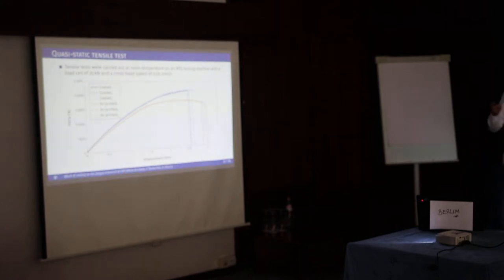Let's start from some static tests. Here I'm only reporting tensile static tests. There is other research that my colleague Tamborino is doing on compressive tests that I'm not reporting today. These are the results for as-printed specimens - without coating - and the coated specimens. We have six tests in total: three for the coated and three for the as-printed. The main results we can see is that as-printed specimens have slightly bigger elongation, while coated specimens have bigger resistance. We did this test preliminary to the fatigue test, only to understand how the coating can behave.